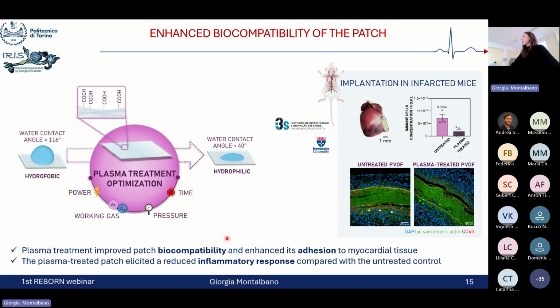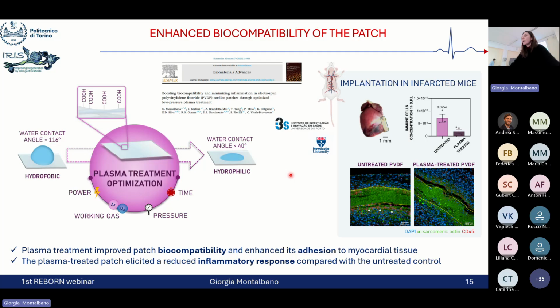And then we could confirm also the higher biocompatibility induced by the plasma treatment, thanks to the collaboration with 2 institution partners, IFRIES from Porto and Newcastle University, that performed a comprehensive biological assessment both in vitro and in vivo that could highlight the improved biocompatibility and the enhanced adhesion in vivo to myocardial tissue. We also could observe from the images how the plasma-treated patch supported a reduced inflammatory response compared with the untreated control. So this was a very large study, so I would like to invite you to read our recent publication on Biomaterials Advances if you want to get some more details about it.